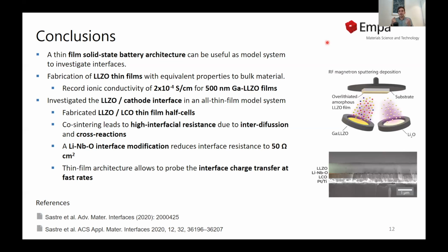Specifically, we introduced a lithium niobate interlayer that is capable of reducing the interface resistance from 5 kilo-ohm square centimeter to only 50 ohm square centimeter. These thin film architectures also allowed us to demonstrate that fast charge transfers are possible between LCO, solid electrolyte, and a cathode material. If you are interested to learn more about our work, you are welcome to check these references.